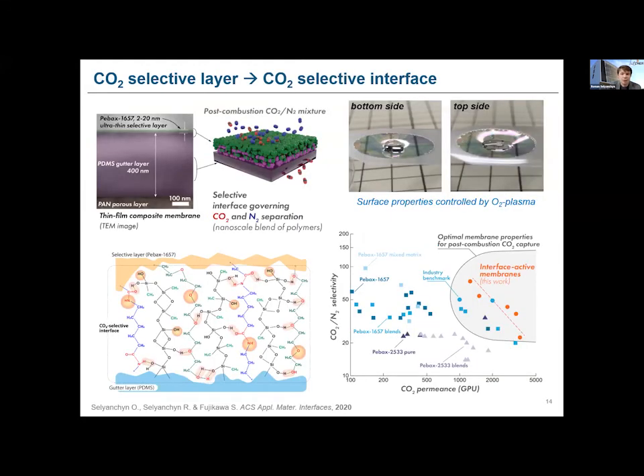And in another major work, we have investigated the thinning of this selective layer, which I already mentioned, in the structure of the thin film composite membrane for the CO2 and nitrogen separation. And here you can see a TEM image of this 3-layer membrane. The porous support, of course, is very thick, but only the top of the porous support is seen here. The gutter layer is around 400 nanometers, and the selective layer just a few nanometers, from 2 to 20 nanometers. We were testing the thicknesses.